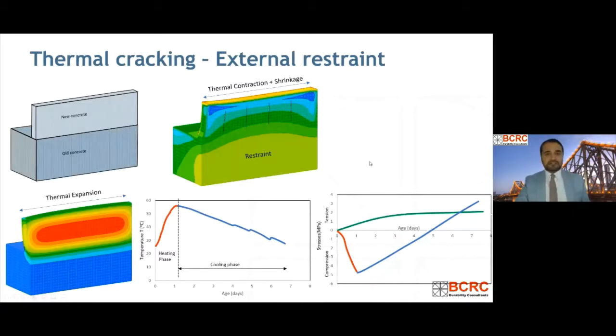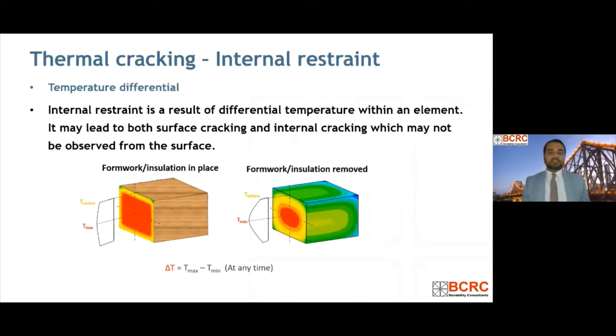Now in mass concrete elements, the main type of cracking that we observe is due to internal restraint. So what is an internal restraint? Internal restraint is occurring due to temperature differential, as I said, because your inner core is too hot and the heat is dissipating from the surface, so you always get a gradient. No matter if the concrete is insulated, you still have a gradient, and even if you remove the formwork, you will get a much steeper gradient at that time.